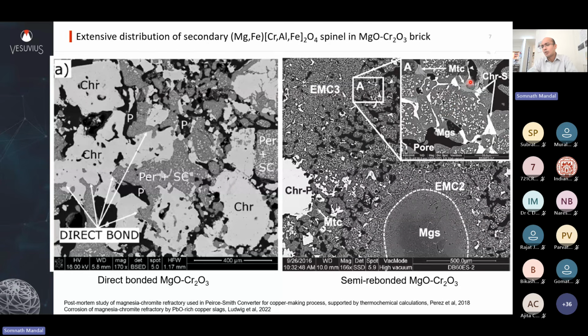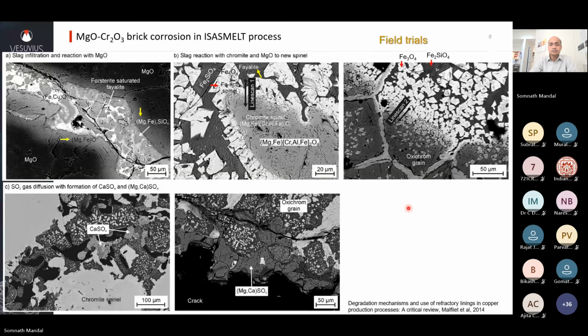And then you have some amount of monticellite, CaO, MgO, SiO2, or CMS phase. So because of this secondary chromite formation, you end up with a very highly bonded, high temperature resistant, high hot strength refractory product. So now let us look at how corrosion of this happens so that we are able to develop alternative refractories. So in this microstructure, you see the magnesia gets corroded on the outside. It forms magnesiowüstite or MgO-FeO solid solution due to the reaction with the fayalitic or Fe2SiO4 slag.